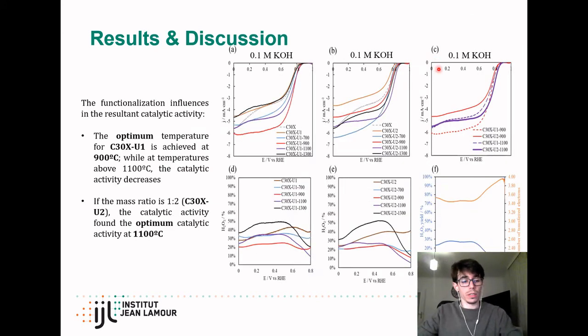So now that we have studied the nitrogen oxidation states of our material, we can move on to the evaluation of the catalytic activity. We can see in figure A that the optimum temperature of the heat treatment to reach the highest catalytic activity is determined to be 900 degrees, while by using a carbon-urea ratio of 1:2, the highest catalytic activity was reached after the heat treatment at 1100 degrees. Putting together all the most promising material, it can be observed that the highest catalytic activity was reached by using a carbon-urea ratio of 1:2 at 1100 degrees, the purple line.